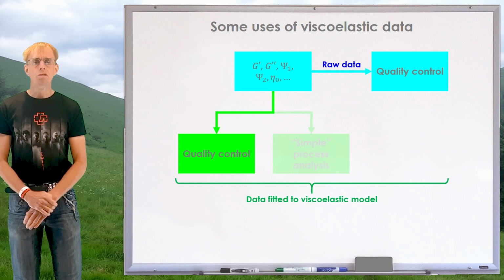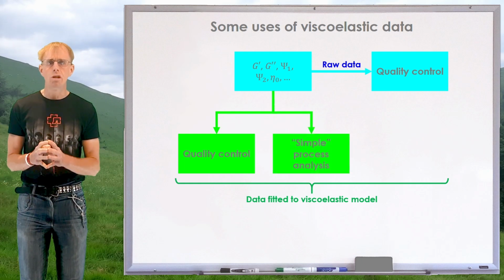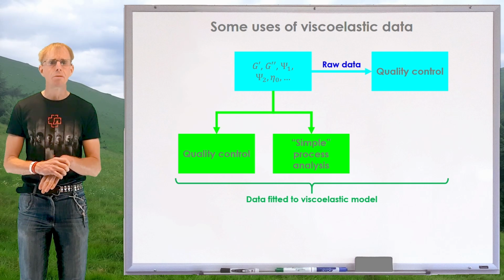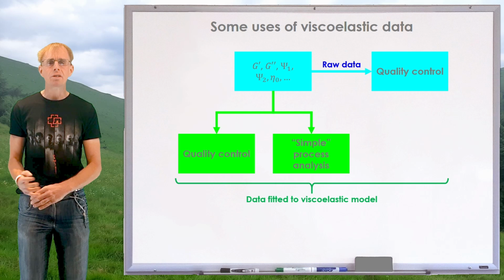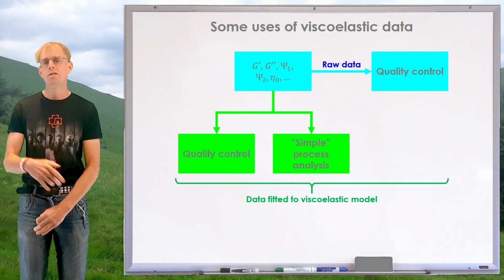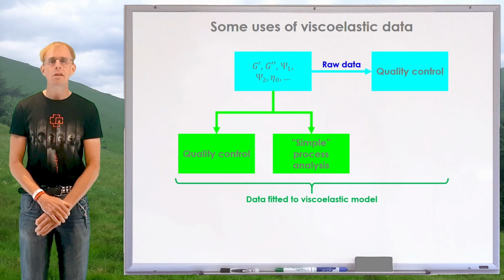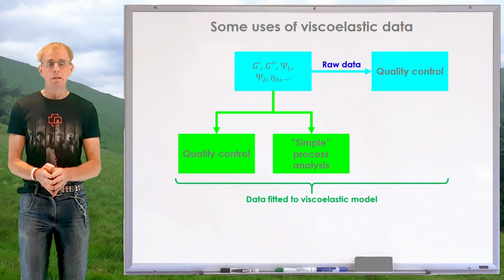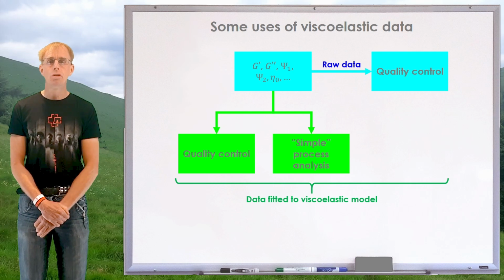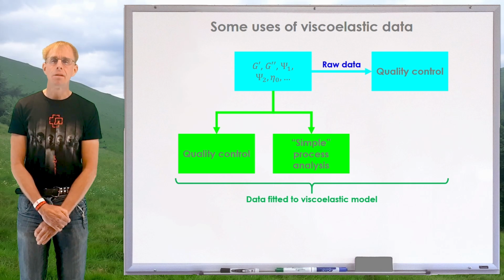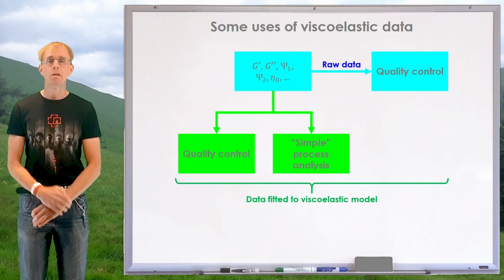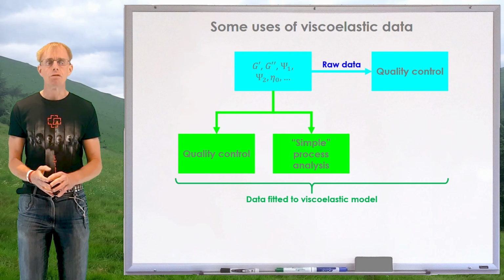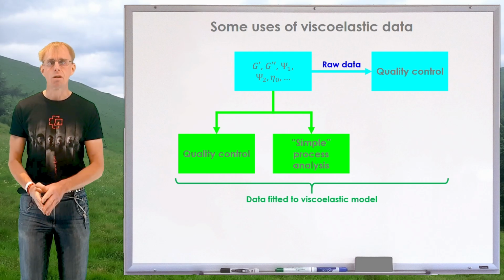What we might also be able to do is to choose an appropriate constitutive model and say, look, fine, okay, we can fit, for example, a 3 or 4 mode Giesekus equation to this linear low density polyethylene. It describes the shear thinning, it describes the normal stress responses, and what it gives us are a couple of parameters that we can now also use to, for example, estimate the amount of die swell, or maybe to estimate the amount of time taken for stress in an extrudate to relax below a certain threshold stress.